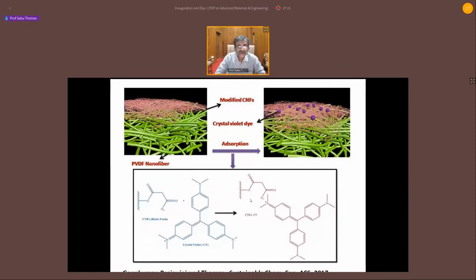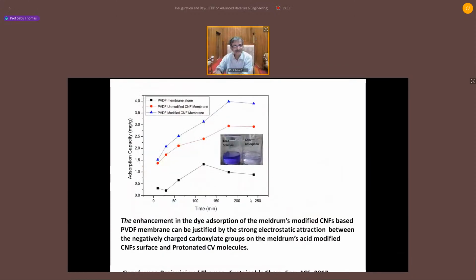You see our dye removal. You can see this paper from ACS. We published in ACS. This is adsorption capacity as a function of time. This is the commercial filter. This is a filter modified by us with nanocellulose. The top one is chemically modified nanocellulose. Look at this. So chemically modified nanocellulose, if you make it and if you give a coating on the surface of commercial filters, you can get fantastic results.